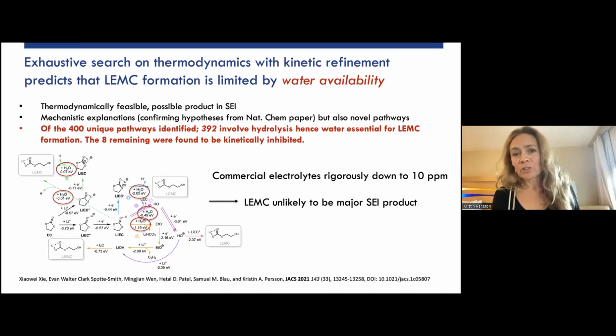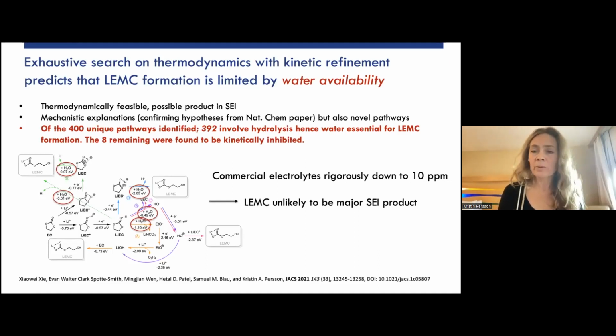But most importantly, out of the 400 unique pathways that we identified, 392, so all but 8, involve hydrolysis of some sort. So water is a key player. And the 8 remaining ones were found to be kinetically inhibited. This isn't completely exhaustive. We couldn't go through all 9 million. We took the steepest ones by delta G and refined those with kinetics, but the vast majority of those paths involved water. Given that commercial electrolytes and even lab electrolytes these days are dried pretty rigorously, it seemed unlikely to us that LEMC, being dependent on water in the electrolyte, would be a major SEI product.